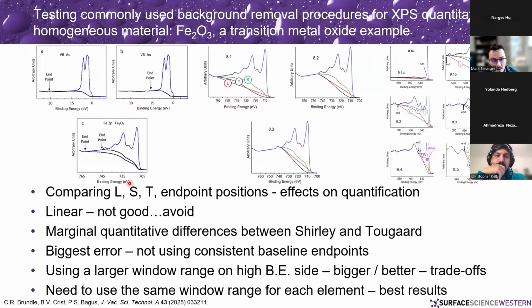And it wasn't just the window size on each element. Each window should be consistent. So if you're doing a 20 eV window in your backgrounds for the iron, you should be doing the same thing with your oxygen. You should be doing the same thing with your carbon. How much change is that going to make?